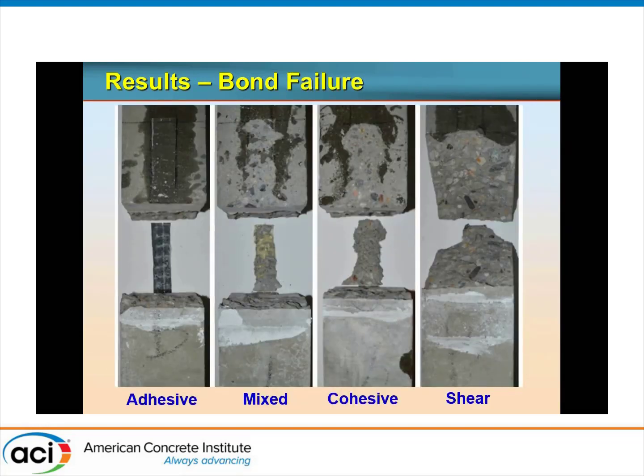These are the failure modes that you could get from this test. So that's an adhesive failure, where failure happened within the resin. We do not see traces of concrete on the surface. And that's a cohesive failure, and by cohesive here I mean cohesive within the concrete, where the surface is entirely covered by concrete. And then this one is kind of mixed between adhesive and cohesive. And this is the one that failed by shear in the concrete. In other words, not a bond failure at all. And that was eliminated. I think there were only 1 or 2 of those out of the 57.